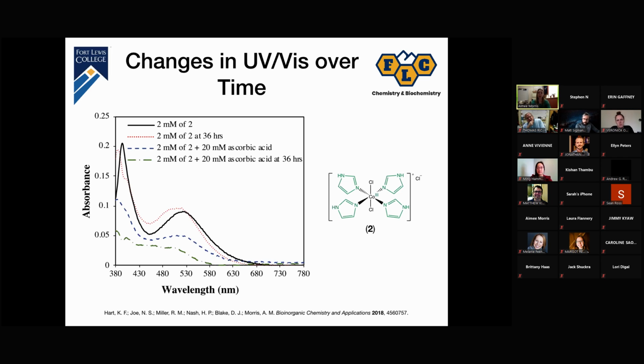And we also wanted to investigate what was going on in terms of oxidation state of this compound. So when I mentioned at the very beginning that our inspiration came from those ruthenium compounds, those ruthenium compounds and their mechanism of action is very, very highly debated in the literature. One of the potential mechanisms of action is that the ruthenium(III) metal center becomes reduced, and it is the reduced form of ruthenium that actually causes a whole cascade of events to act as a chemotherapeutic agent.